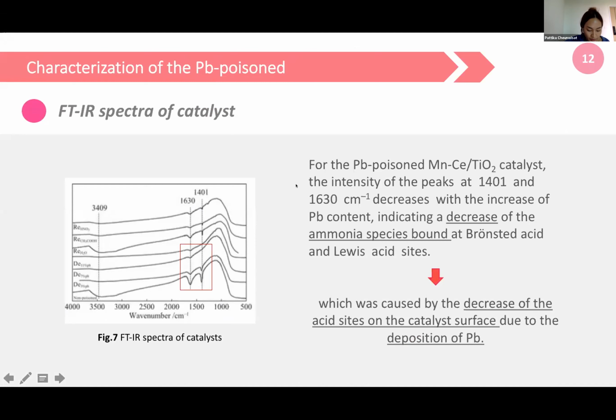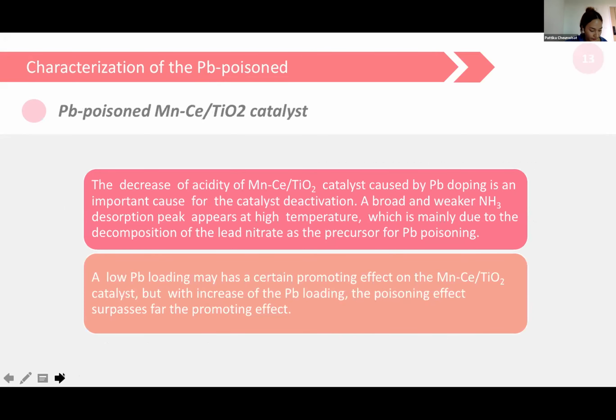The intensity of the peaks at 1401 and 1630 cm⁻¹ decreases with the increase of Pb content, indicating a decrease of the ammonia species, which was caused by the decrease of acid sites on the catalyst surface due to the deposition of Pb.